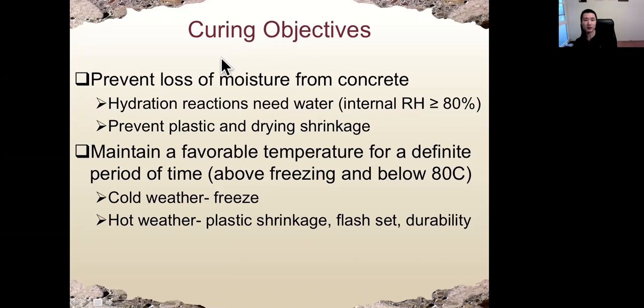The reason we cure concrete is to prevent loss of moisture from it. Remember, hydration - the chemical reaction between water and compounds in cement - needs water, at least 5 to 7 days, the longer the better. Inside the concrete, if the internal relative humidity is less than 80%, the hydration process will stop. That's one of the major reasons we need moisture at the early age of concrete.